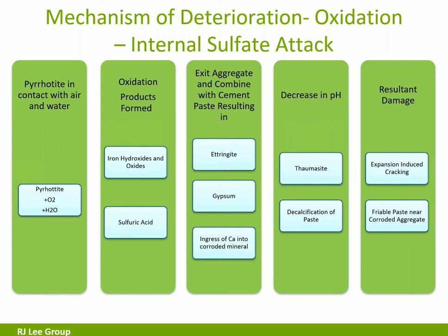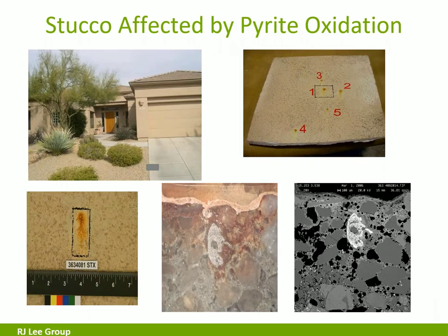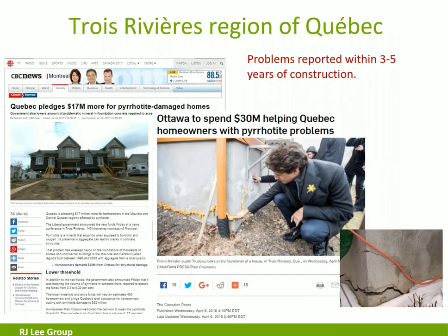The first started showing up probably around 2009, I think, maybe 2006, in the Trois-Rivières region of Quebec, where the problems really started within just a few years of construction. These foundations began cracking. And in the United States, we have an area of Connecticut which has shown the same or similar kind of damage. These structures were constructed in the early 80s. It really came out of one quarry in that area. It was a schist. The damage took about 10 to 30 years mostly to be able to show up.